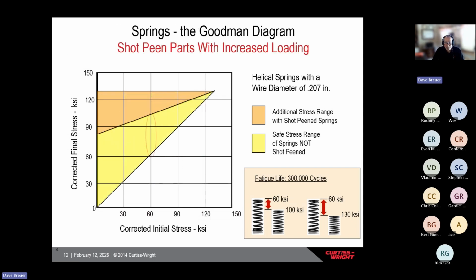So in most situations, most of our customers are interested in getting more life from the shot peening. And in some cases, our customers are interested in putting more load through the part. So typically you can increase the load on the part about 10 to 30% and get the same amount of life as the non-shot peen situation.